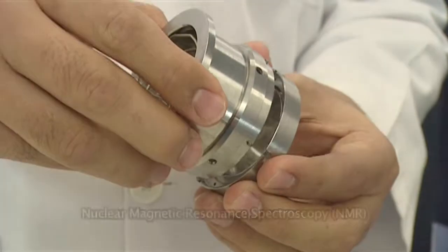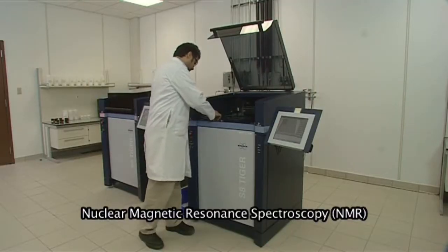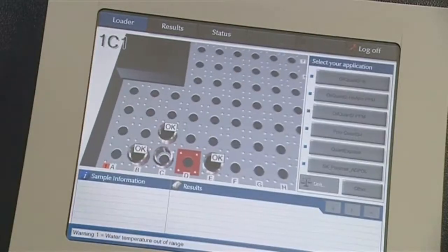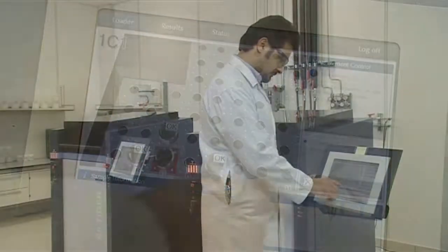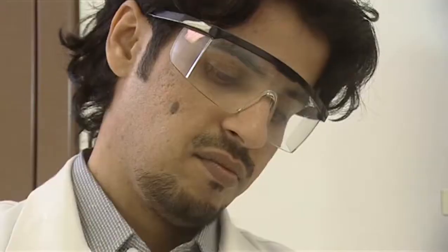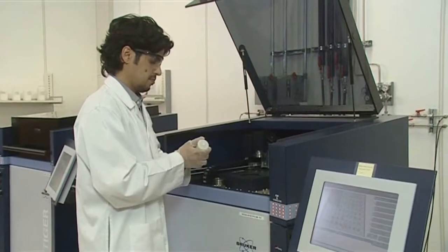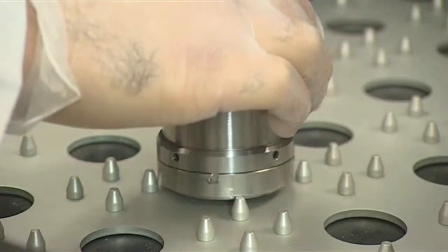X-ray fluorescence is the fastest and precise technique of performing qualitative as well as quantitative analysis of elemental composition of the polymer. The polymer's stability, strength, durability is mainly controlled by the additives added and catalyst residue present in polymer.